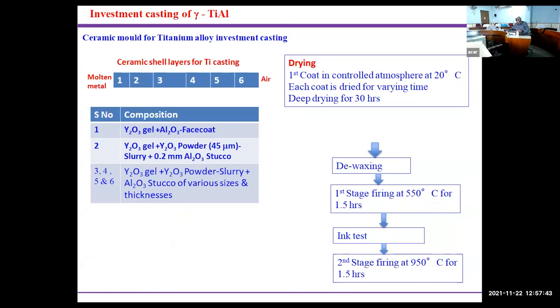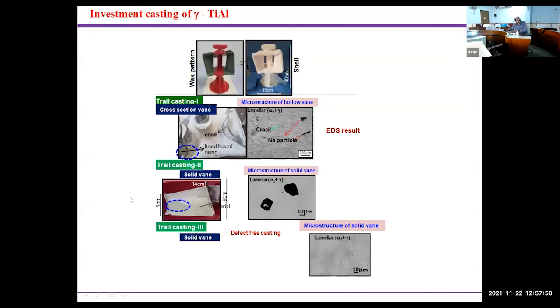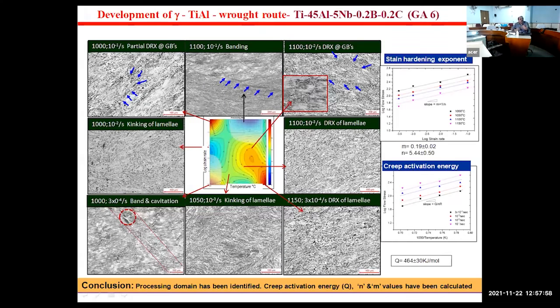We have kind of optimized the shell now. So here are the first few castings of the investment cast material. Here I'm showing the lamellar microstructure, and some of the newer gamma aluminides can also be wrought processed, but at much higher temperature than 1150, 1200 degrees centigrade.